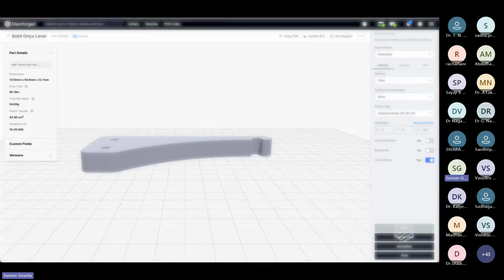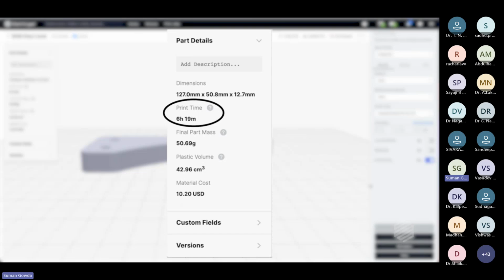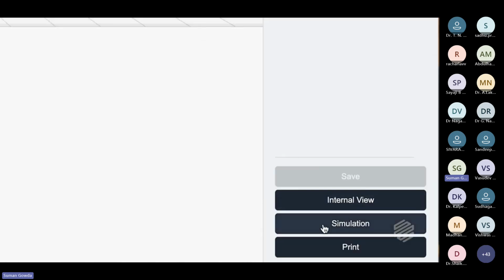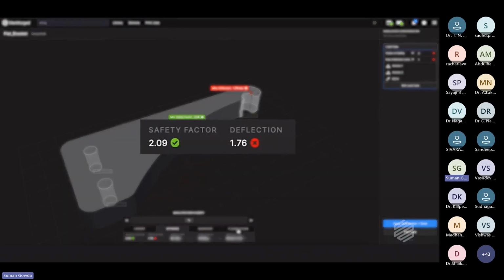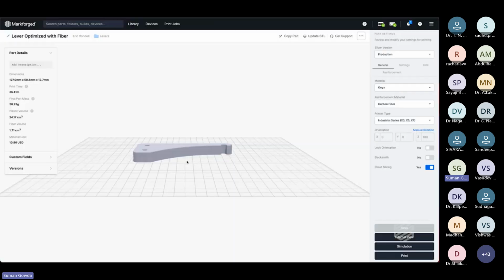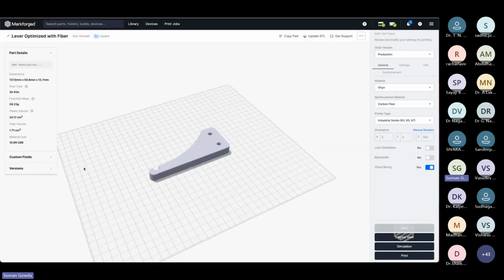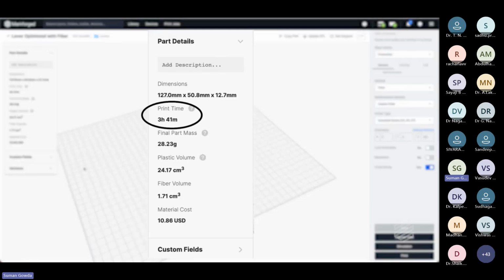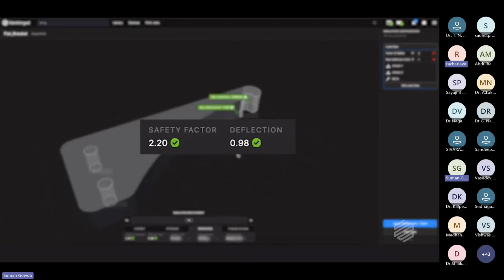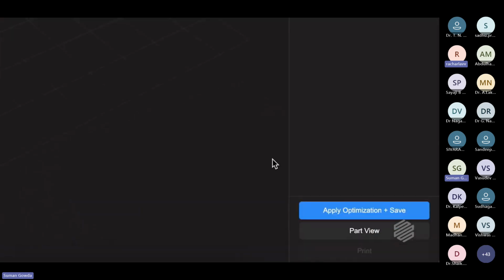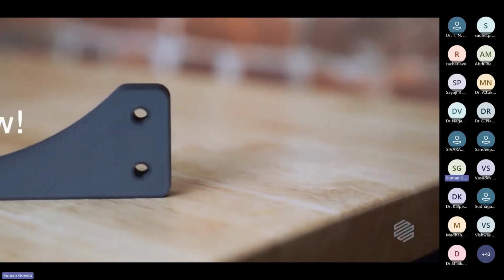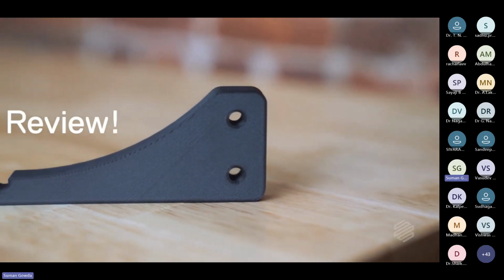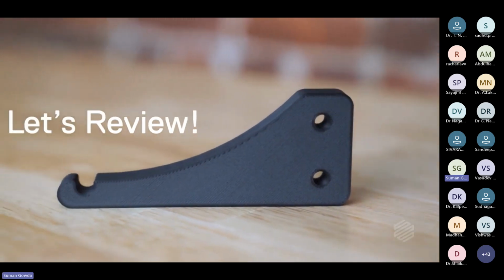The second print, with solid infill, took 6 hours and 19 minutes to print. It meets the factor of safety of 2, but has a maximum deflection of 1.8 millimeters. The third print, optimized using simulation, took 3 hours and 41 minutes to print. It meets the factor of safety of 2, cutting print time almost in half with the same required strength. With simulation, it took only a few minutes to simulate and optimize this part.